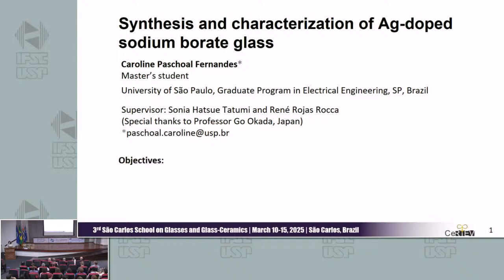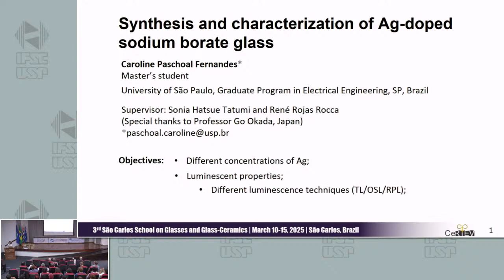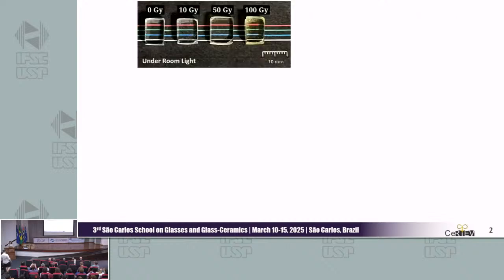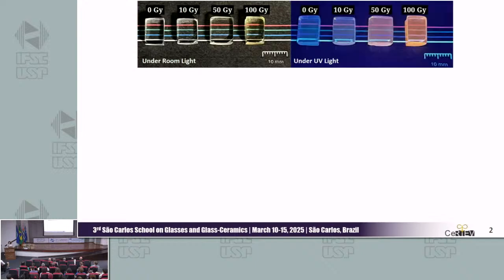The main objective is that we test different concentrations of silver and test different luminescence techniques. For that, the main application is the dosimetry field. We can see here the doped sample under the room light, and we already noticed the difference because of their dose. And under UV light, we can check the creation of a luminescence center at 100 grays with orange emission.